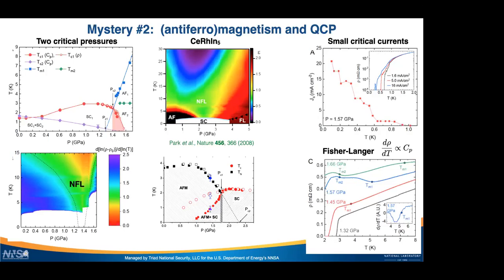And this has been seen before, of course, but only in antiferromagnetic systems. You may have a super zone gap, for example. In that case, the resistance is expected to go up, which means that the ordering vector for this magnetic order may not be commensurate with the lattice. I would like also to note that we're not the only ones getting to this conclusion. The Japanese group, and this is a paper led by Aoki, they also, from experiments not under pressure, but in high magnetic fields, come to the conclusion that antiferromagnetism is a likely possibility, actually.